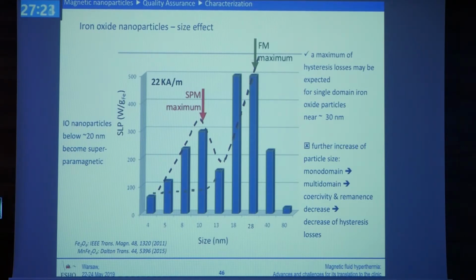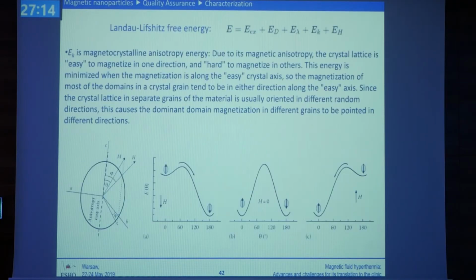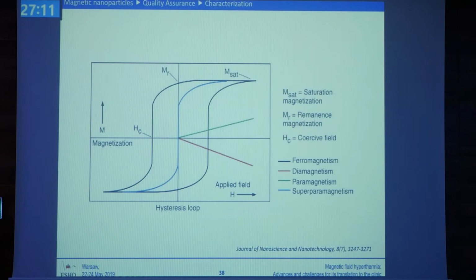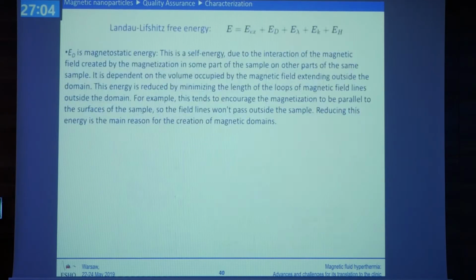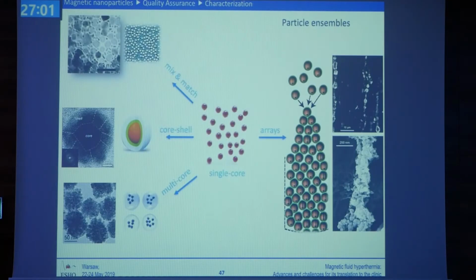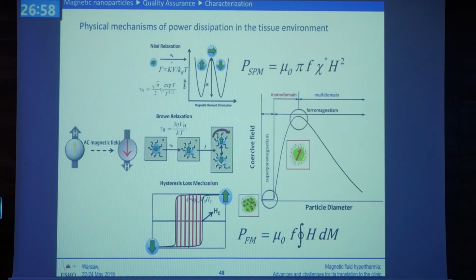And when they become larger, and you have several domains, as I showed, inside the nanoparticles, then the energy they can leave to the space is smaller because the hysteresis loop becomes smaller, because the coercive field becomes smaller here. So there are two ways for giving energy to the environment for the magnetic nanoparticles. The first way is for the very small nanoparticles, the superparamagnetic ones. You can see on the top that each nanoparticle spin can change direction, but this leaves energy to the space around. This is called Néel relaxation.